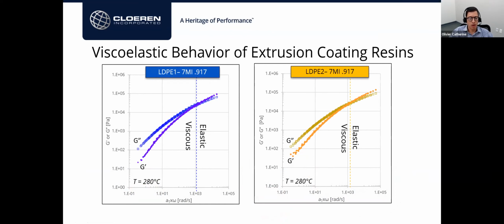So for example, I've plotted here a study that I ran some years ago to characterize the viscoelastic behavior of extrusion coating grade polyethylenes. On the left here, the blue material is LDPE1, which is a 7 melt flow index material with a density of 0.917. And as you can see, it's a very standard extrusion coating grade material, and I will use it as a reference and compare that to other extrusion coating candidates.